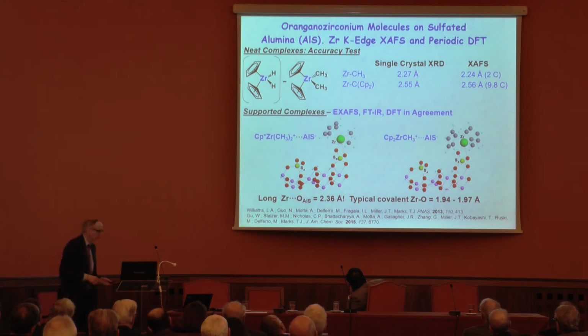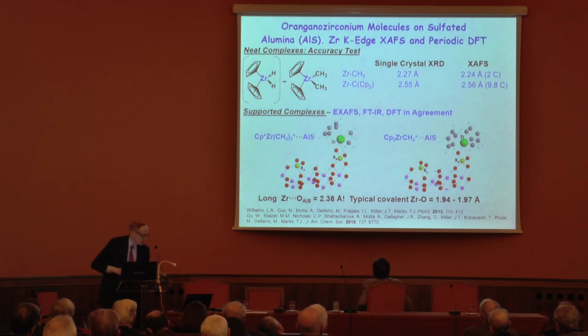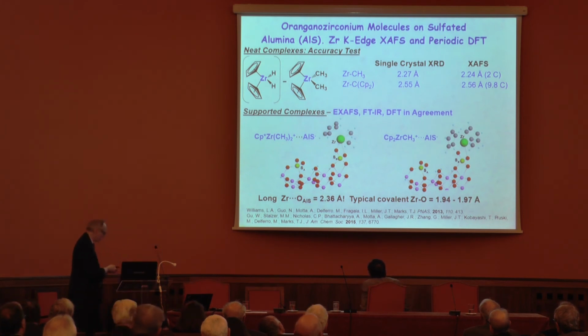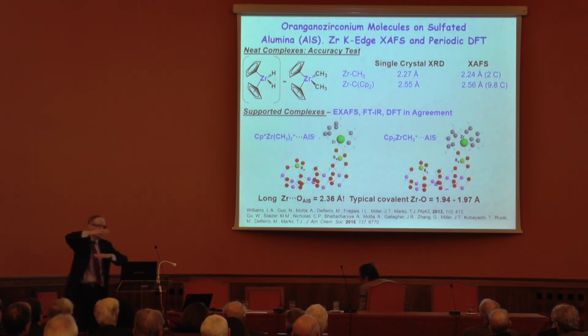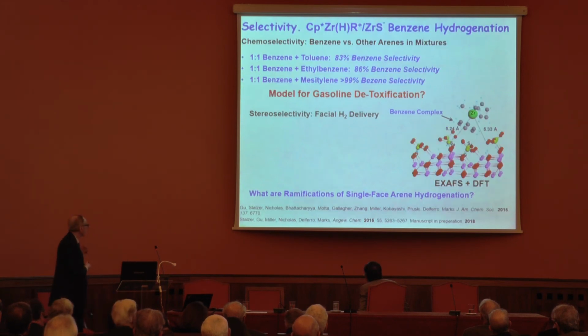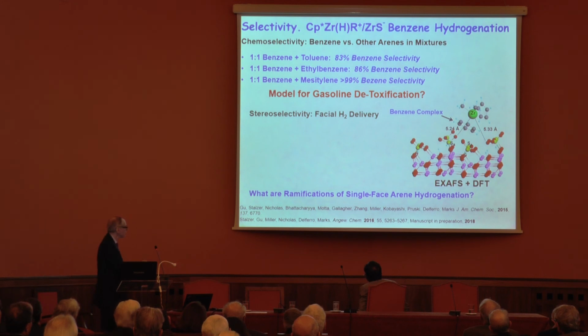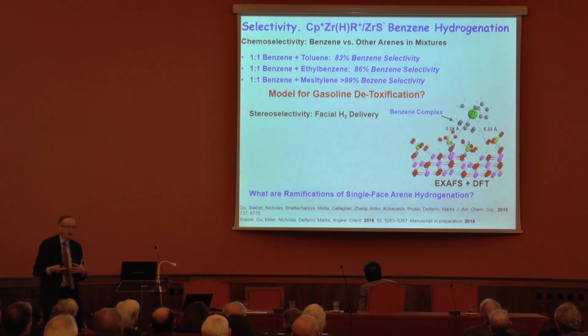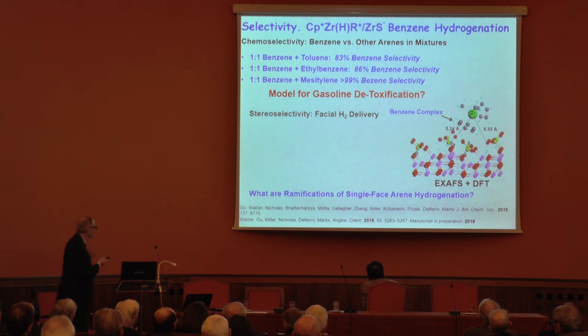And the reason is that the cation is supported on essentially a sea of electron density of this oxide surface. And here's the XAFS data. This is Alessandro Mota sitting right back over there, one of the people who did the DFT calculations. We can see this very loosely bound cation, and you might wonder, to finish the lecture, what is it good for? Here's what it looks like. Essentially the substrate is docked between the zirconium and the anion. So this is a benzene complex. It hydrogenates benzene. And you sort of say, wait a minute, that's a d0 14-electron cation. They don't do that. They do that.